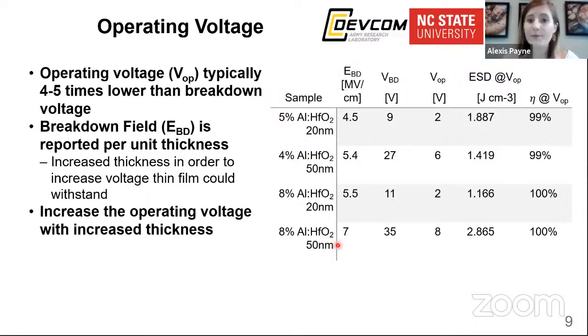So this table shows you your breakdown field, which is reported per unit thickness. As you can see, if we increase the thickness, we actually get an increase in your breakdown voltage. So your 50 nanometer films have much higher breakdown voltages than your 20 nanometer thin films. And that shows up, obviously, in the operating voltage. The 50 nanometer films can be run at a higher operating voltage.